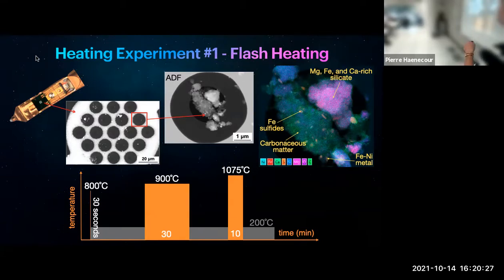You can see here one of the samples on the silicon nitride film. You can see the particle with the silicon nitride film around it, and that's the heating material. You can see the EDS map. It's basically a composite map of nickel, iron, calcium, sulfur, silicon, magnesium, oxygen, carbon. The only thing I want you to see is that it's a lot of different colors. The only thing I want to point out is that there is both iron sulfide, and there's a lot of carbonaceous material. All the greenish colors is carbonaceous material. Carbonaceous material is mostly composed of organic matter. And then magnesium, iron, and calcium-rich silicates, and then some iron nickel metal around it.